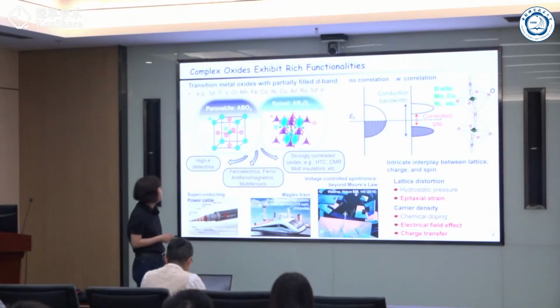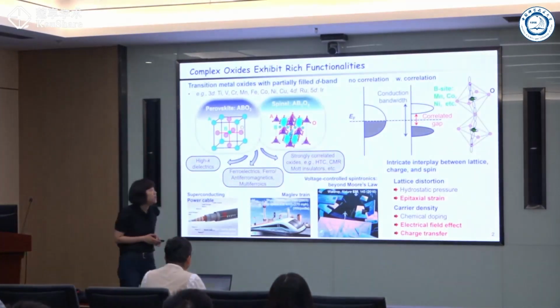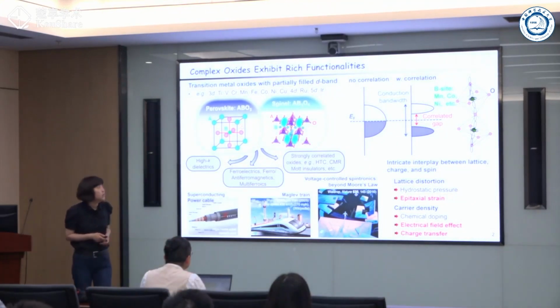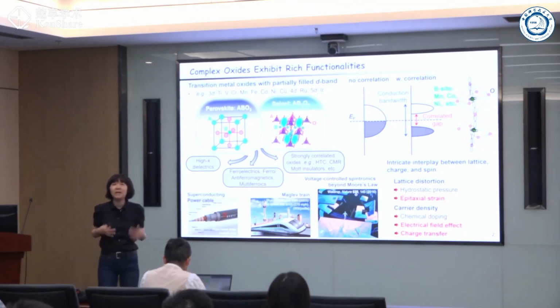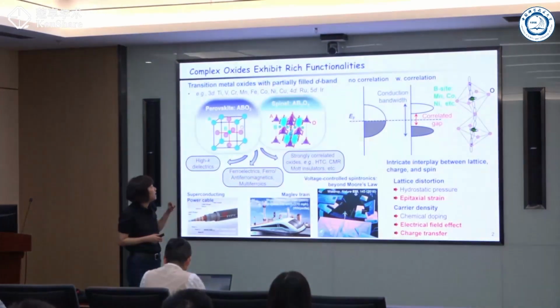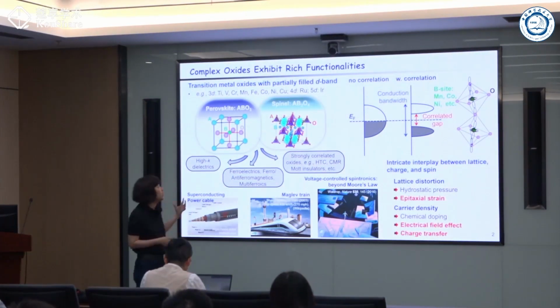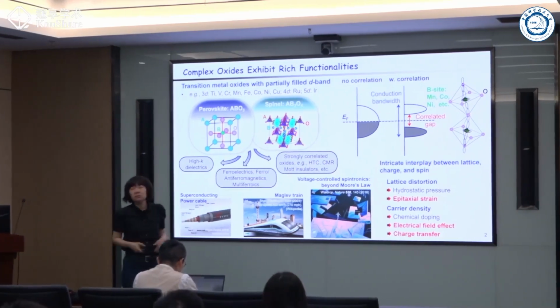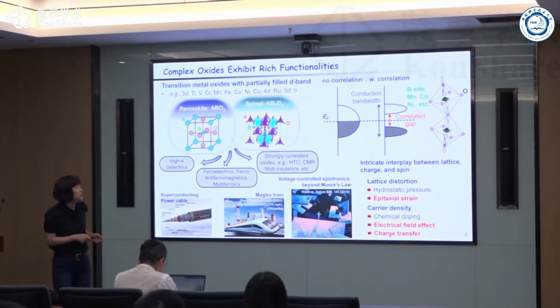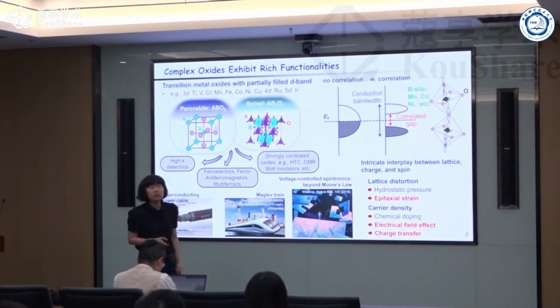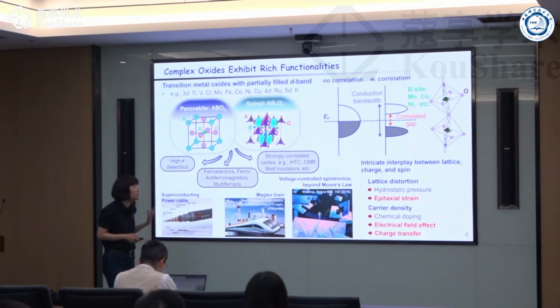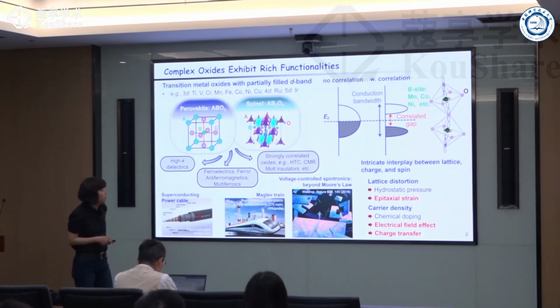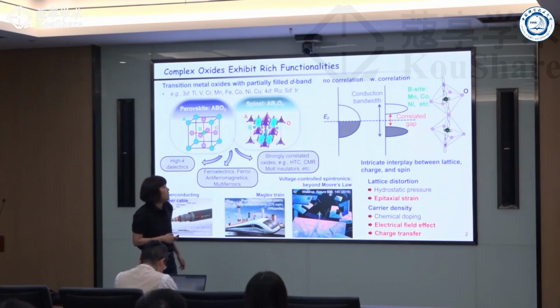So what we're interested in is strongly correlated oxides, specifically Mott insulators. If you look at these transition metal elements, they have partially filled d bands. So from a simple band point of view, those are metals. But if the electronic bandwidth is comparable with the strength of the on-site Coulomb energy, it will open a gap. And this gap can be controlled by tuning the interaction, leveraging the interplay between lattice, charge, and spin.